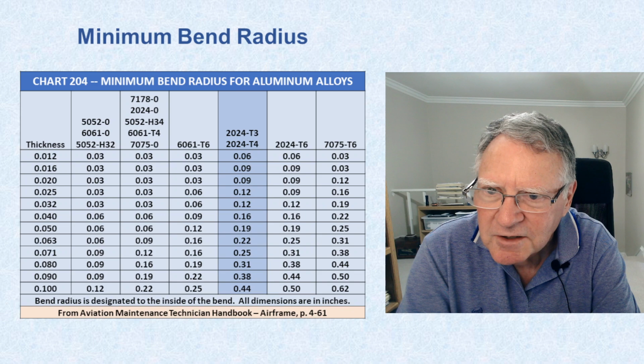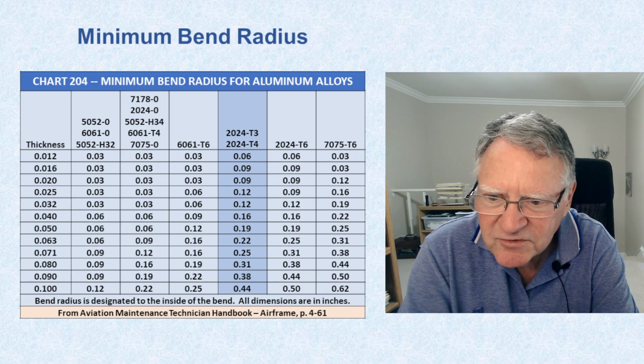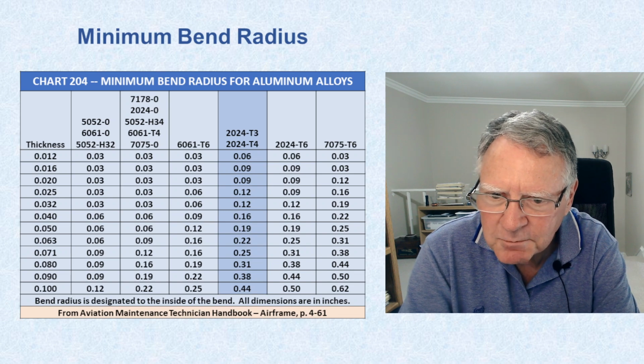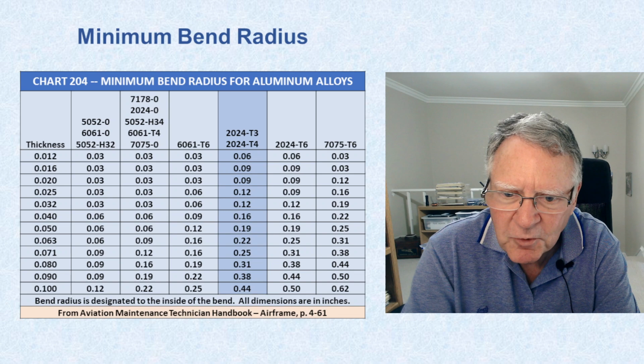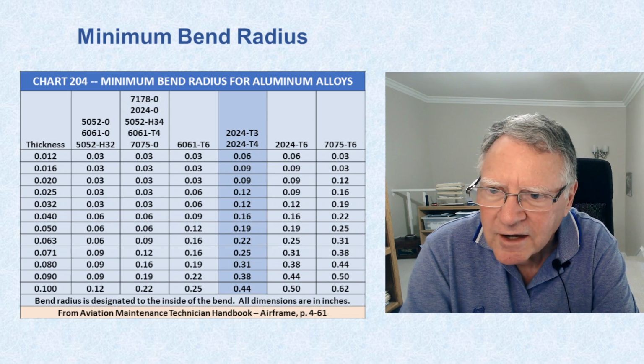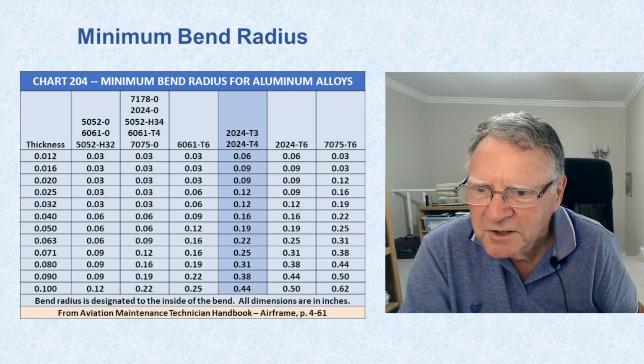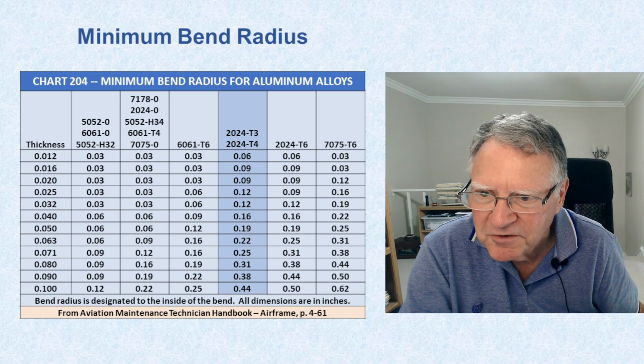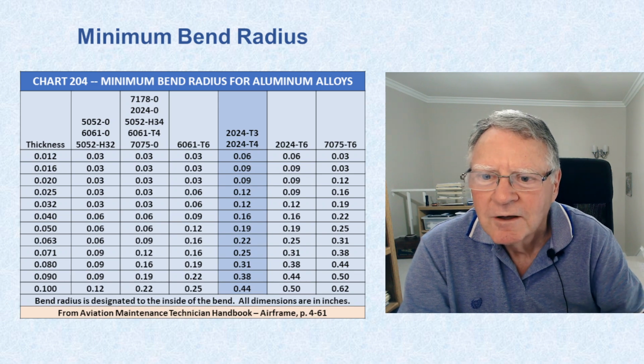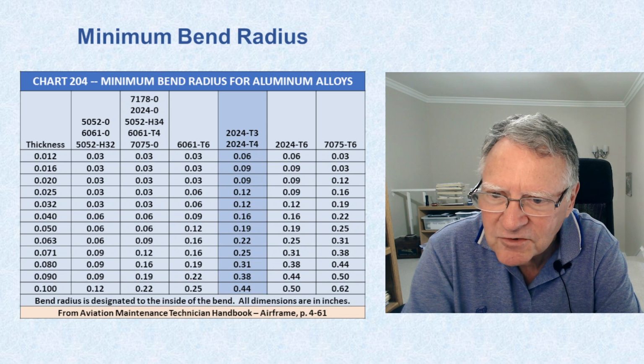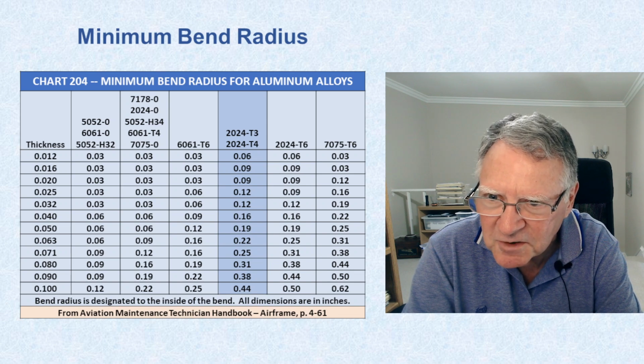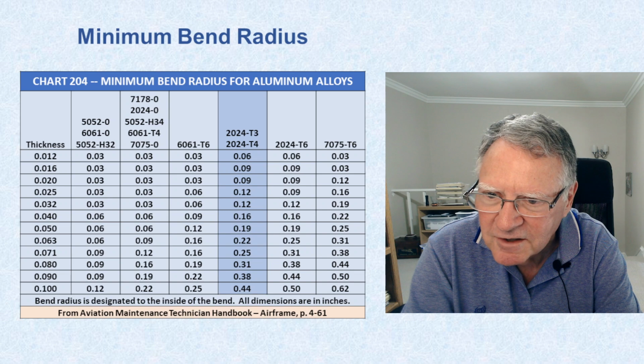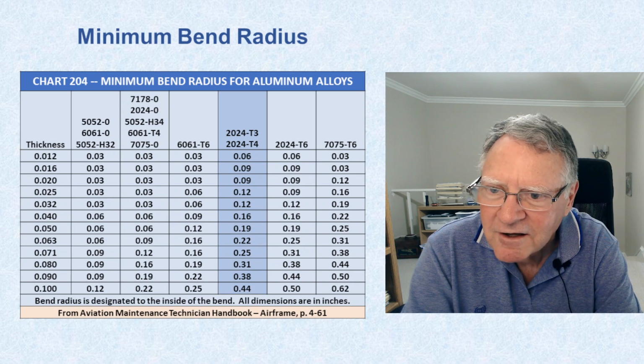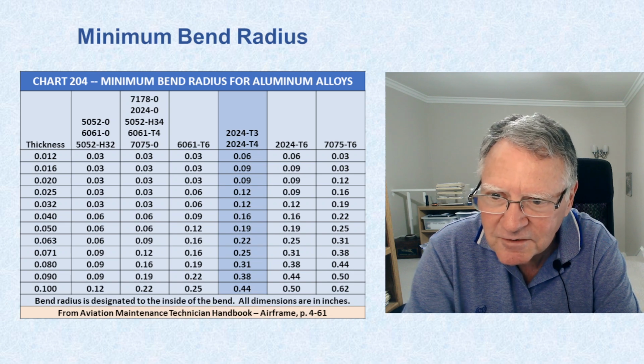Okay, this is a table of the minimum bend radius for various aluminum alloys, and it's taken from the Aviation Maintenance Technician Handbook, Airframe, page 4-61. And let's just pick an arbitrary thickness, let's say 40 thousandths. You see that for the alloys on the left side of the table, they're all basically -O's. They're basically just annealed, and they're probably fairly pure aluminum. And they have a fairly small minimum bend radius, 0.06 inches.